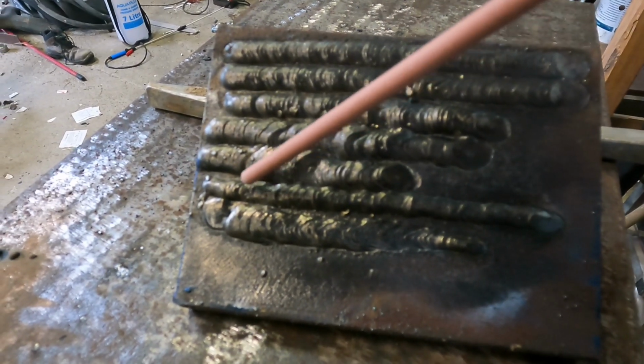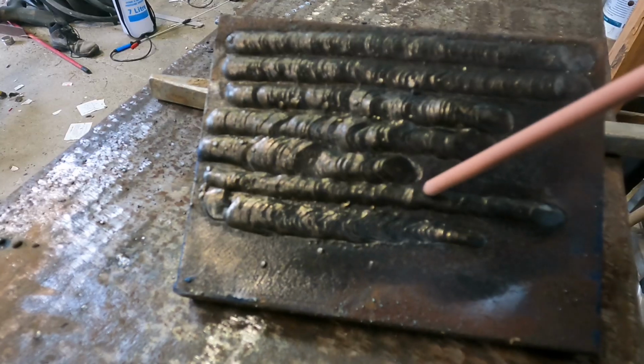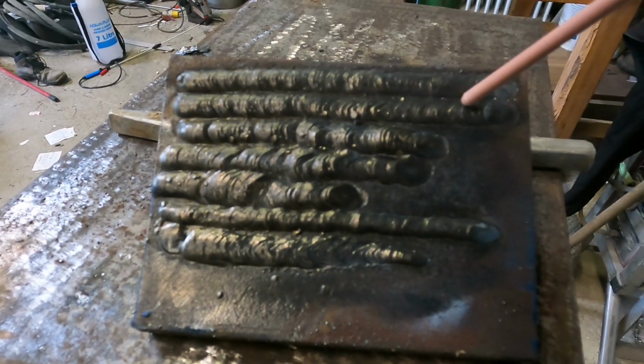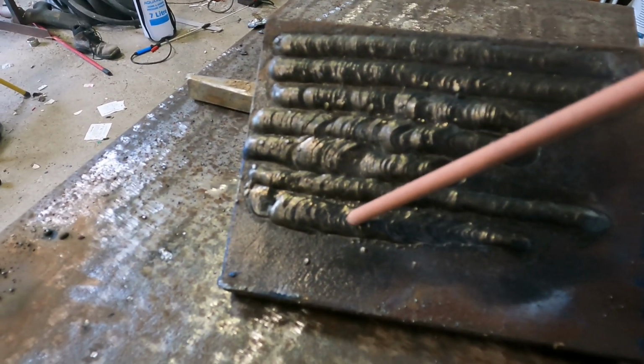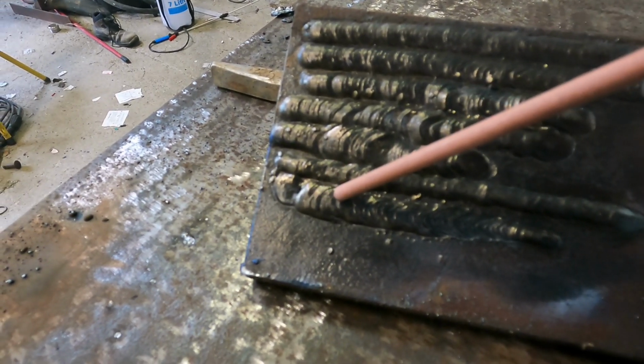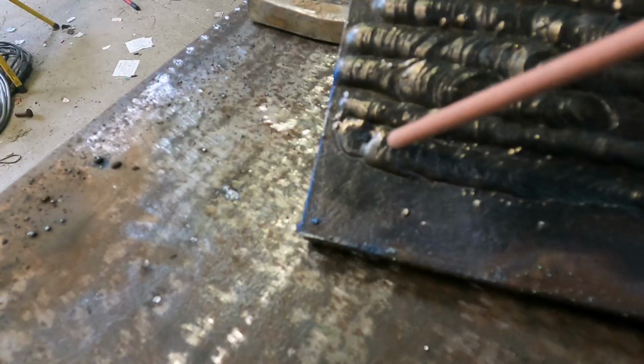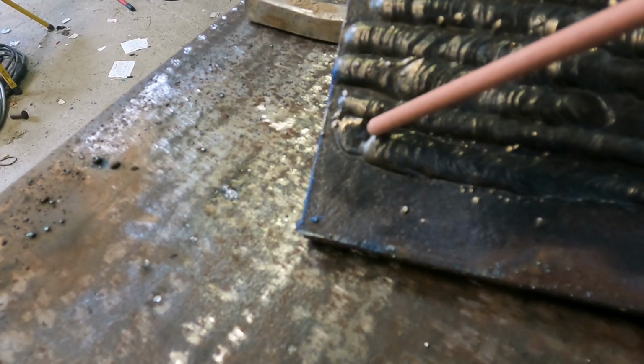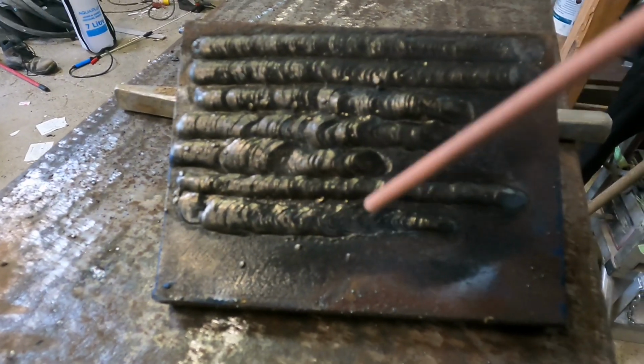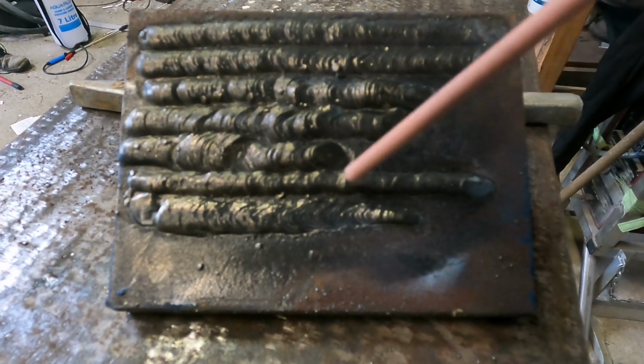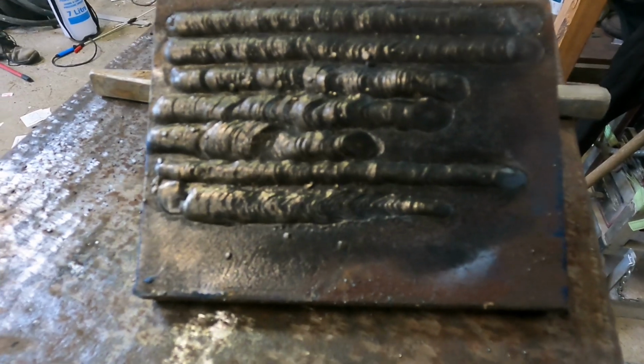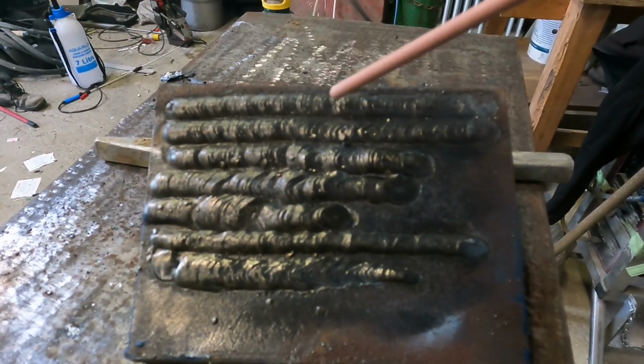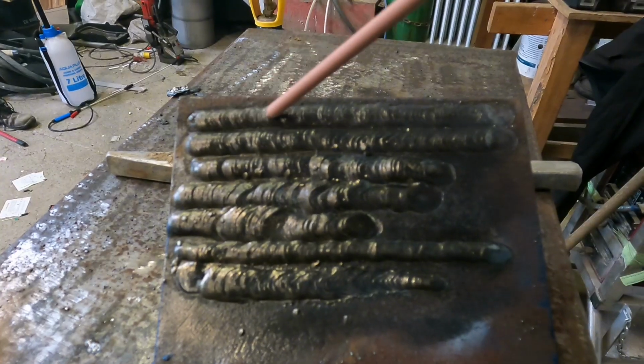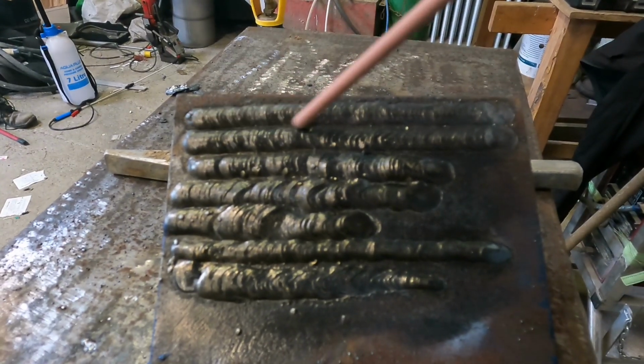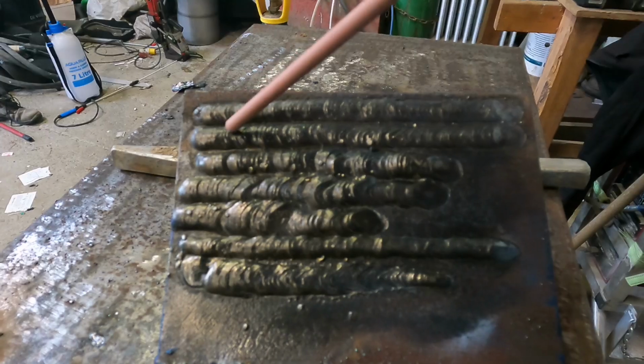This one here then, we put down to 80 amps, which didn't come out too bad, but still a little bit narrower than these top two. And then this last one here was where we went up to maybe 160, 170 amps, way too hard. We actually have a small little slag trap there, but a lot wider than the rest of them. And again came down to the end of a rod here nearly, so we really burnt it out altogether. So if you could keep them all like that, the main thing is to get plenty of practice. Just keep practicing your straight runs, your technique.